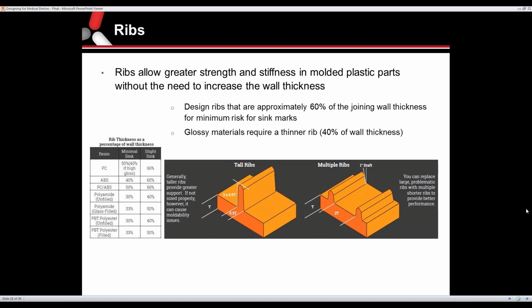Right, and when you're designing your ribs, you also want to take into consideration your draft. So if you have a really tall rib, if you're going 60% of the nominal wall, those ribs can get pretty thin if they're tall. So you run the risk of not filling or trying to pack out and sticking in the mold and breaking off. And as always, whenever possible, avoid sharp corners, things like that. Any kind of radiuses and so forth always improves the moldability of the particular part.